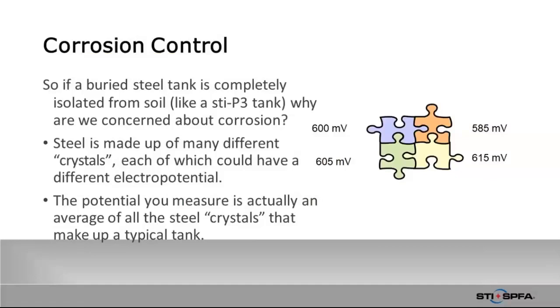One aspect is that these steel plates are made up of essentially crystals. I'm sure a metallurgist would get fired up over my description of that, but there may be different spots even on a steel plate, and even on a plate as it's worked into a tank, that may end up with different values. And those are connected. Here's just sort of a puzzle piece description of it: you may have a value of 585 millivolts next to 600 millivolts. So you're setting up a corrosion cell between almost like microenvironments. The potential when people are measuring for cathodic protection is really just an average of all the steel. And so what's going on is sharing of electrons across to protect that plate.